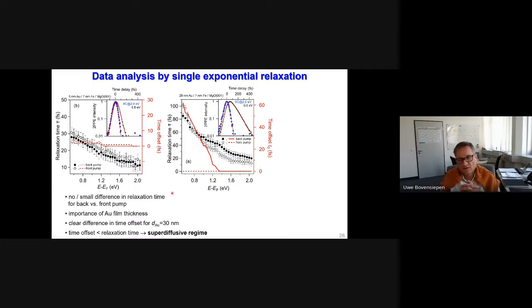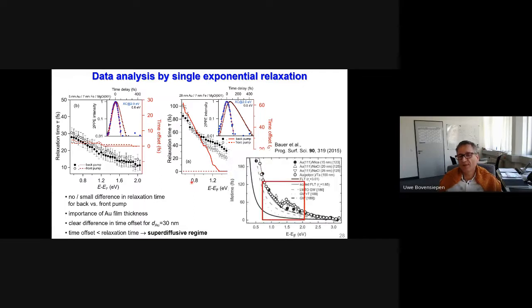But before I do this, let's compare quantitatively the time offset in femtoseconds and the relaxation time in femtoseconds. So you see here this time offset ranges from 0 to 60 femtoseconds and the relaxation time is from 0 to 100 femtoseconds. So that means while the electrons propagate through gold, they scatter. And these are individual scattering processes, since we see here this relaxation time is on the same order of magnitude as the time offset. So this means that we clearly operate here in a superdiffusive regime. So question answered. Now let's go to this discussion of the relaxation time.